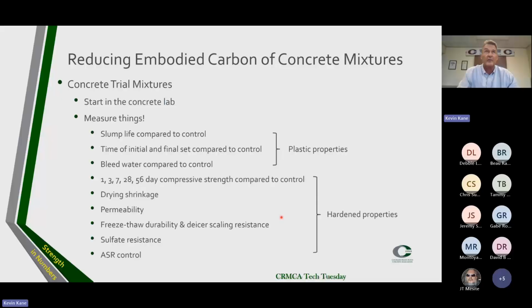Start in the concrete lab. Measure things, like Zach talks about. You can't control what you don't measure. Start in the concrete lab. Measure the slump life compared to a control mix. Measure your time of initial and final set compared to control. Measure your bleed water compared to control. We never used to pay much attention to bleed water. We kind of took it for granted until we started realizing that, wow, type 1L cements don't bleed as much as type 2 cements. So then we started really paying attention to it.